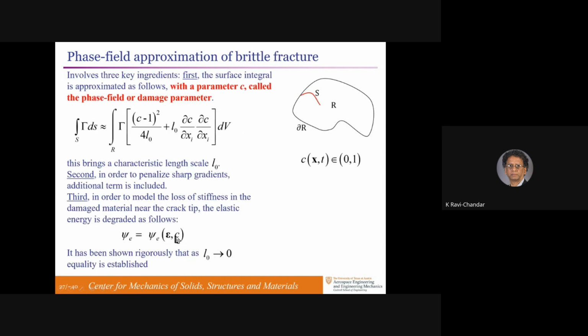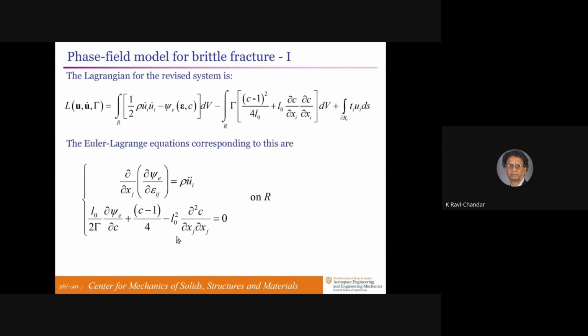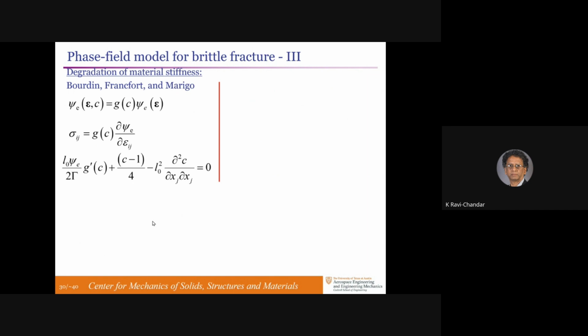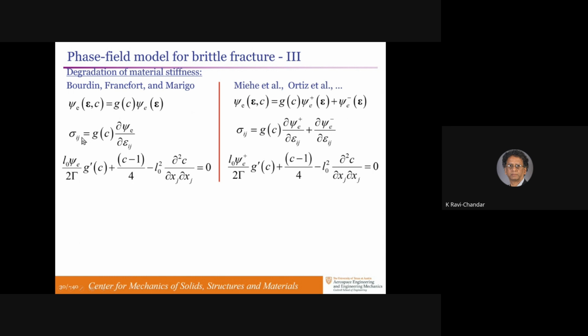depends not just on the strain, but also on the damage parameter C. So you get two equations, one for equilibrium of the mechanical forces and the other one for the evolution of the phase field parameter. And I'm not going to go through this partially because I'm jet lagged, but the details are a little bit tricky. The basic idea is you take this strain energy to be the undamaged strain energy multiplied by some function of the damage parameter C, and that gives you details of the damaged elastic property as well as the evolution of the damage function itself.